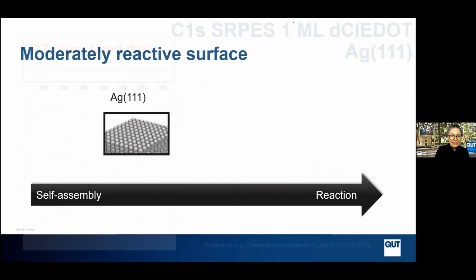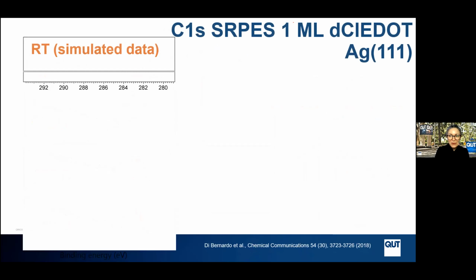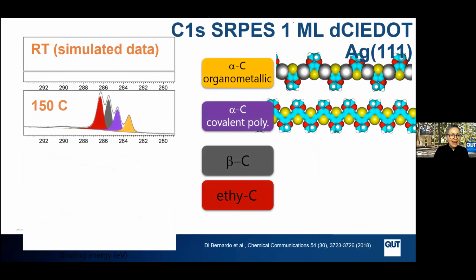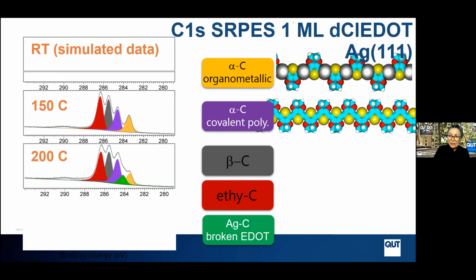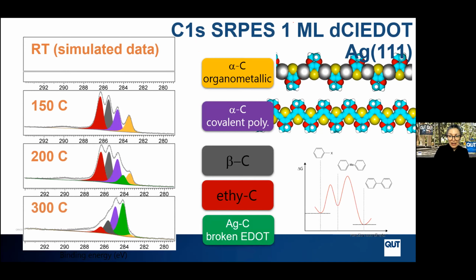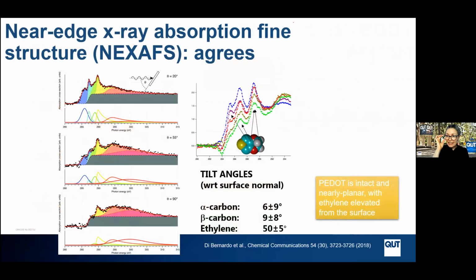So silver was our last ditch effort, and disappointingly, the molecule didn't even stick to it. But we could, in fact, stick the molecule to the surface when it was heated. So at 150 degrees, we get a nice dissociative adsorption where the molecule breaks enough that it doesn't desorb off the surface again. And as it turns out, that breaking was the carbon-chlorine bonds. We're able to form both an organometallic and a covalent polymer after deposition at 150. The molecule starts to break with additional heating, but we have now the recipe that we needed to make the